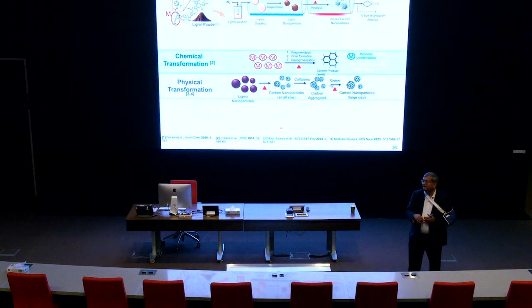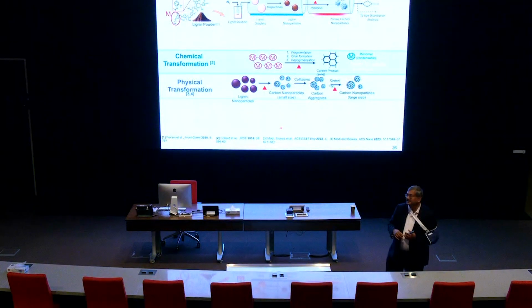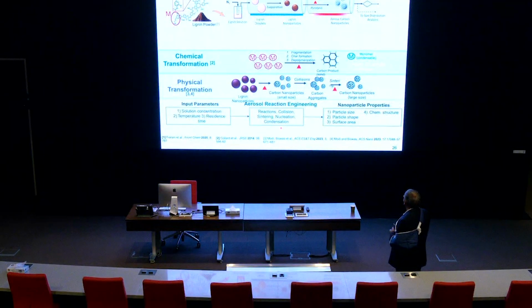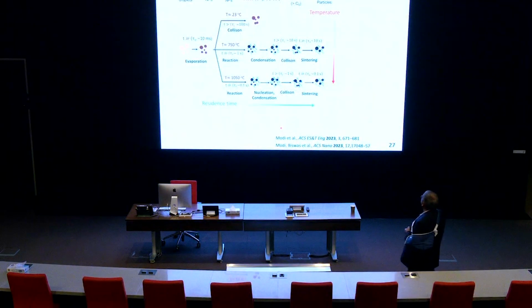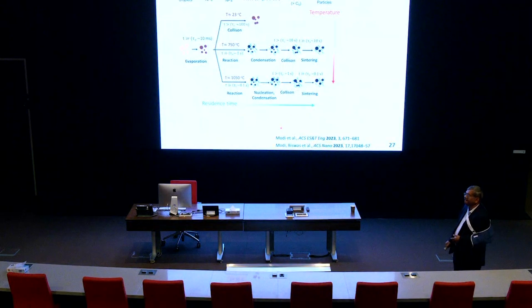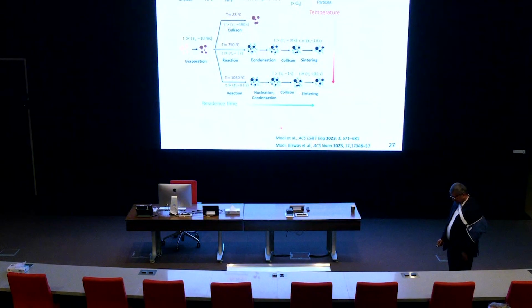Yeah. It was a very nice talk, but my question is on slide 27. For example, if you go to slide 27, here we talk about the nucleation, collision, and so on. But you also showed us that from lignin, you are able to make these carbon particles. And the size of the particles tends to vary. And the variation in the size, have you done the elemental analysis on these particles? Are they only carbon, or do they consist of other elements, hydrogen, nitrogen, or so on?